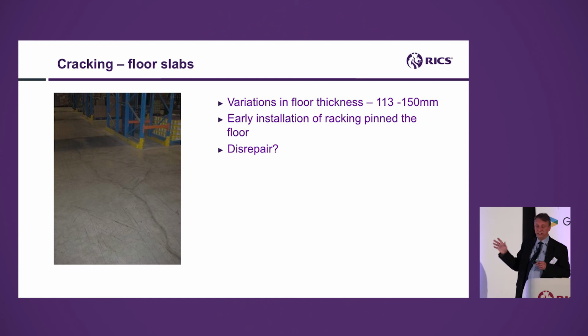So first off, why is it cracked? Is it just shrinkage? What we found is that they put their racking in, and this is serious racking because it went up about 10 lifts, with all their bottles of vinegar. It was a food distribution warehouse. There was quite a big load on these legs. They'd gone in fairly early, so they pinned the floor in place and restricted its ability to do what it wanted to do, which was shrink, and so therefore it had cracked.